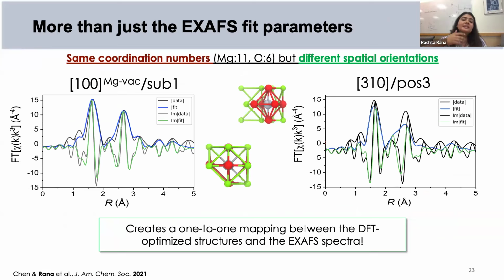The other important thing that I want to highlight here is that when we talk about conventional EXAFS fitting for atomically dispersed catalysts in particular, or well-defined materials, if we are restricted to just the coordination numbers, we can have multiple structures that come out of it. And this is just one example that I'm showing you here. These are two different structures which have the same coordination of magnesium and oxygen to the platinum atom, but their spatial orientations are different.